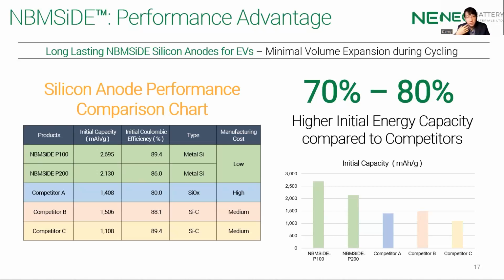And because the sole silicon itself has so much battery capacity, our initial capacity is about 70 to 80% higher than our competitors. What this means is that Neo Battery Materials just needs 5% of our silicon anodes in a lithium-ion battery, while competitors need 10%, or 2 times as much. So lithium-ion battery manufacturers can realize higher capacities or runtimes for the batteries while using less silicon, saving more money, and getting more bang for the buck.